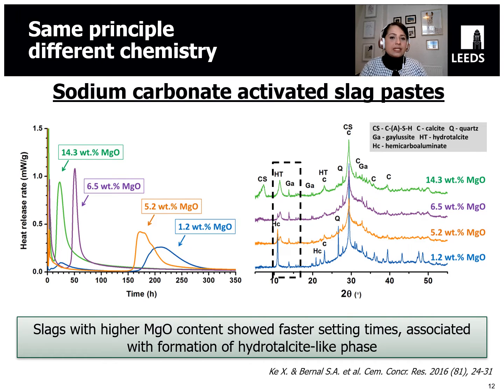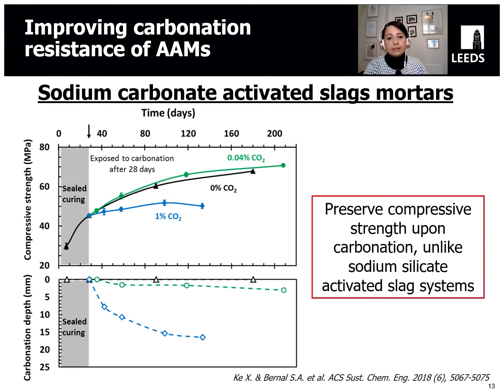So I will say this was another nice discovery, because for the first time in many years we could demonstrate that sodium carbonate activated slag cements could be produced, that we needed to select the right material for the right activator. So not all activators are suitable for all slags, but we could also potentially develop materials with improved durability. And this is exactly what we did.